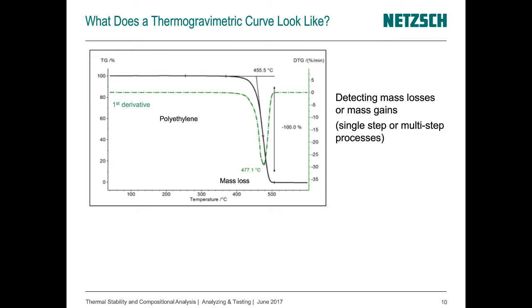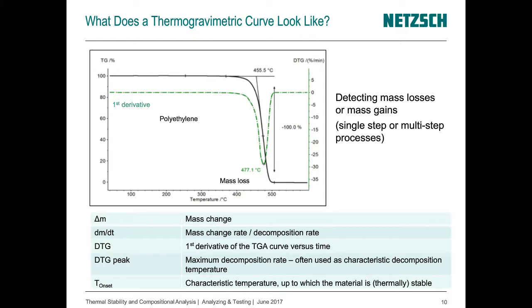In the derivative, which is also called the DTG curve, we can see a peak, and the peak temperature is around 477 degrees C. This is a characteristic value which is often used to characterize the mass loss effect. Additionally, we see another temperature, the so-called extrapolated onset. This extrapolated onset is the intersection of two tangents. One tangent is drawn at the curve before the mass loss starts, and the other one is drawn through the inflection point. And here we have a value of about 456 degrees C. The onset mentioned in the table below is a little bit more shifted to the left side.